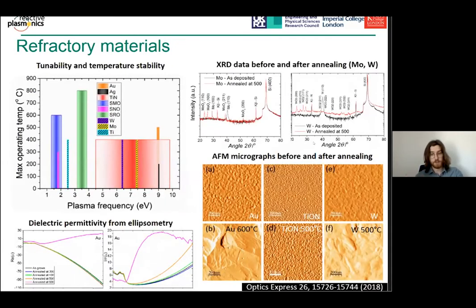But if we're looking to use these materials in practical devices, we're also interested in their temperature stability. So we compared the temperature stability of noble metals, refractory metals, transition metal oxides, and transition metal nitrides in order to identify and map out their operating temperatures, and again, their spectral tunability wavelengths, as we can see in this here. So to do this, we deposited thin films of these materials using electron beam deposition, reactive magnetron sputtering, and pulsed laser deposition. And we completed an annealing study where we heated each of the samples for 1 hour in air from 100 degrees, gradually increasing the temperature in 100-degree increments.